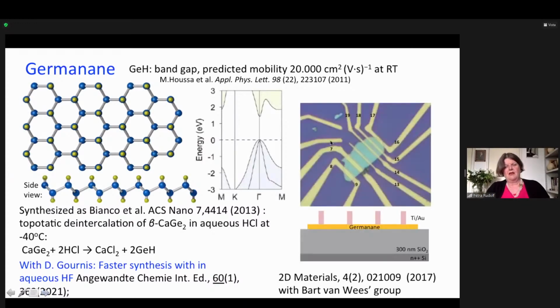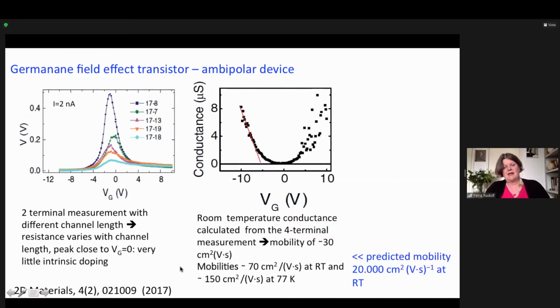For example, my colleague Bart van Wees, who is just above me, made this device with it to measure how it behaves. And what he found is that the resistance varies with channel length, and that there is a peak close to zero. So this is a material which has very little intrinsic doping and which behaves quite well in conductance. It's an ambipolar device like graphene, but of course we are still at the beginning as far as the quality of the material is concerned, because the mobilities are far, far lower than the theoretically predicted mobilities. But that was the same with graphene in the beginning. So we have hope that this will improve in time.